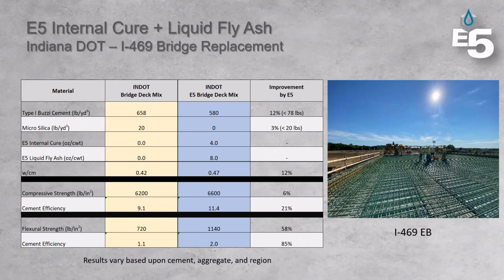When you do that, it doesn't travel upward. So you can use more water to hydrate the cement and get those properties that you need without forcing it through chemical, right? We're consuming the water, we're not allowing it to degrade the durability. So we can use more water in our mixes and use less chemical. When you do that, that lowers the influence on slump loss, working time, things like that, because it's not produced by a chemical reaction, it's produced by hydration.